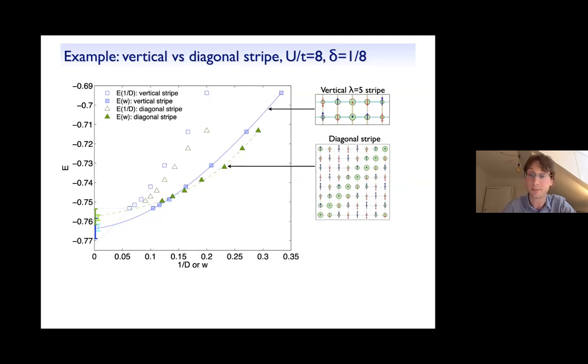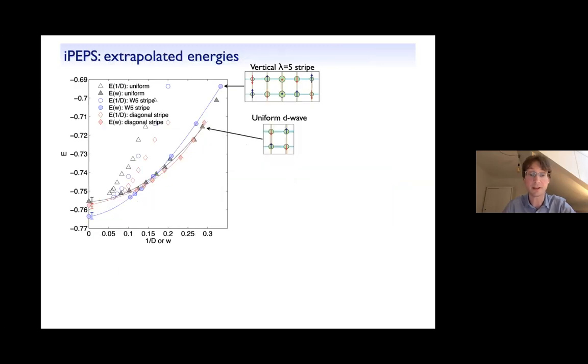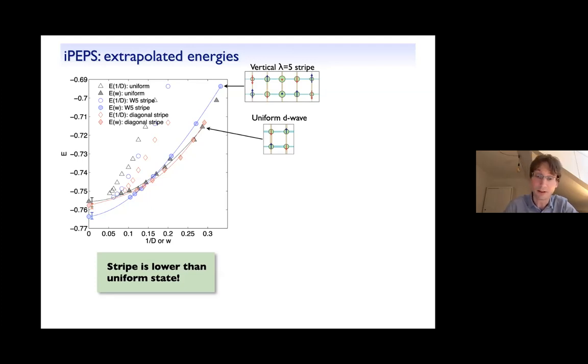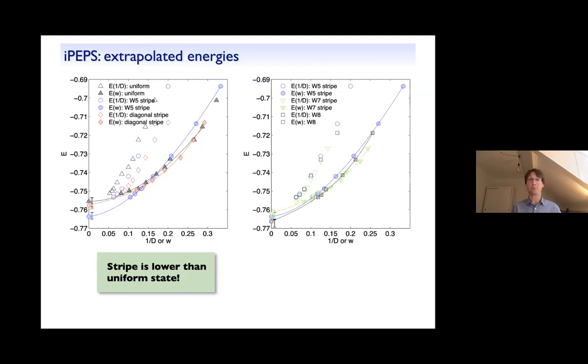Here I show you an example, a comparison of the period 5 stripe with the diagonal stripe. If we take the extrapolation from this, we conclude that the period 5 stripe is lower than the diagonal. Now we can do the same comparison between the uniform D wave state and the stripe state. And if we extrapolate here, we clearly find that the stripe state is actually lower than the uniform state. Which is then the answer to the question we had in the beginning, which of the two is really lower. But now we can move on and also try to find the preferred stripe period.